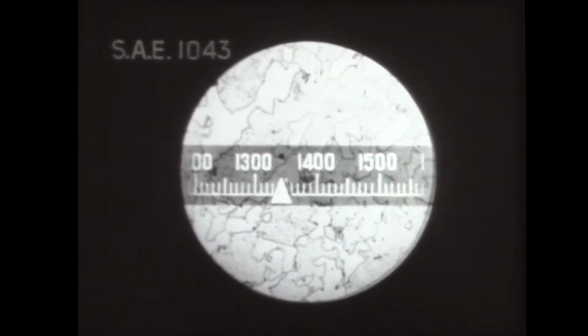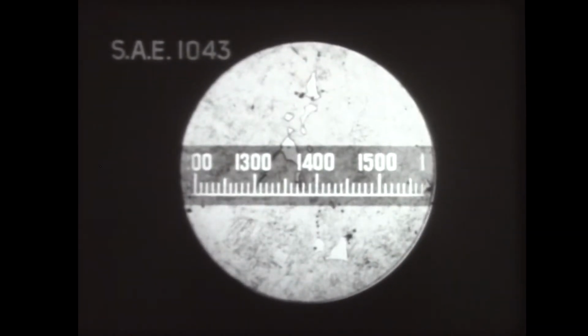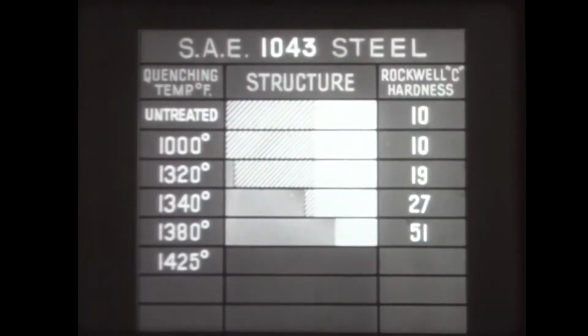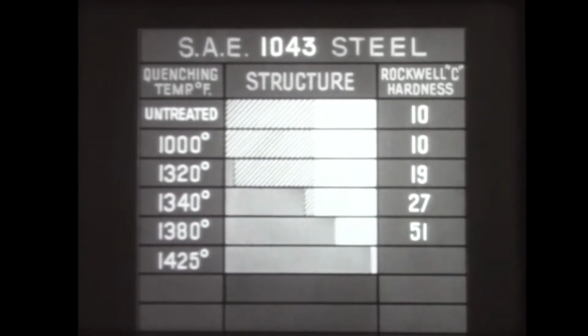When the steel is heated to 1,425 degrees and quenched, the micrograph shows that the structure has become almost all martensite. Only a little of the original ferrite is left. With its structure almost entirely martensitic, the steel is close to its maximum hardness. It is now 58.